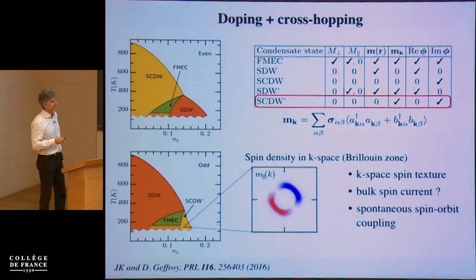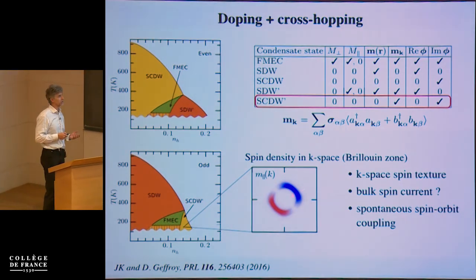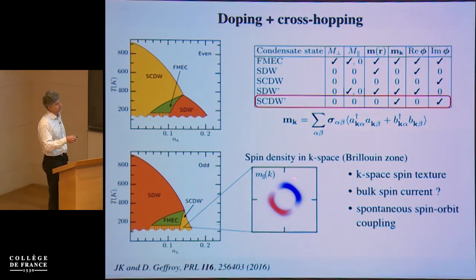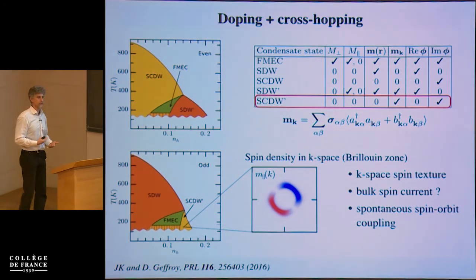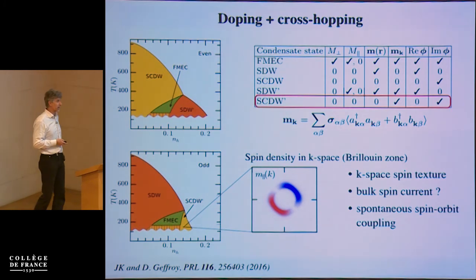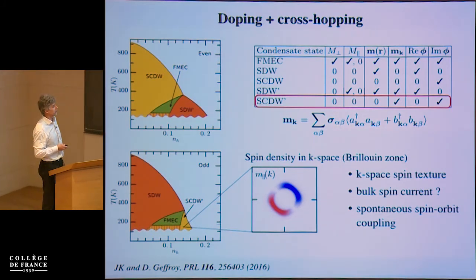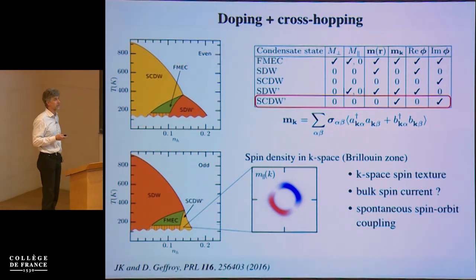This is also not the correct way to think about it, because the contribution to the current depends on the group velocity. We have here two bands, and in our case, they have opposite group velocities. So you cannot really read off spin current simply from the fact that you have some spin texture in your system.